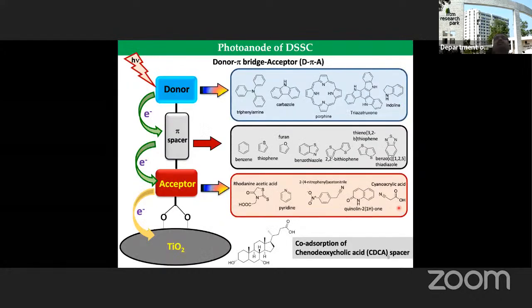Generally, the photoanode, which is the one which harvests light, consists of a high band gap semiconductor like TiO2, which is about 3.1 electron volt. These high band gap semiconductors adsorb the dye and anchor the dye by a chemical bond, as I have shown here. The donor is the part in the dye which can absorb the sunlight. It will get excited because of the sunlight, and the electron in the exciton that is produced will flow through this pi spacer and through the acceptor because of the electronegativity gradient. So those excited electrons will flow like this. Finally, through this bonding, it will be injected into the conduction band of titanium dioxide.